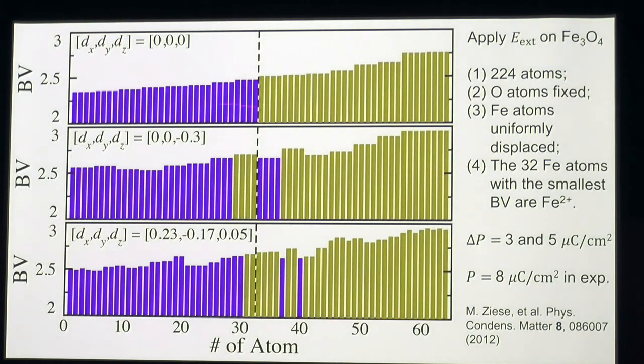In this slide, we show more details about the mechanism of polarization flipping in magnetite. Here, in each primitive cell, it has more than 200 atoms and 64 iron involved in charge ordering. As a result, because of the huge computational cost, we cannot use first principle method to simulate the electric field. Instead, we use a semi-classical method. We assume that each iron has approximately the same dynamic matrix. As a result, we can simulate electric field by uniformly displacing the iron atoms.